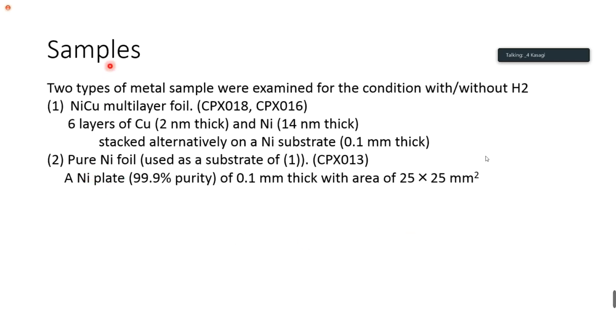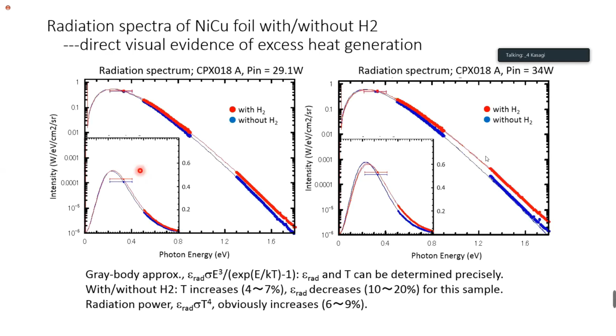Samples we tested. Two types of metal samples were examined: nickel copper multilayer foil, 6 layers of copper and nickel, and also pure nickel foil. So let's see the result.